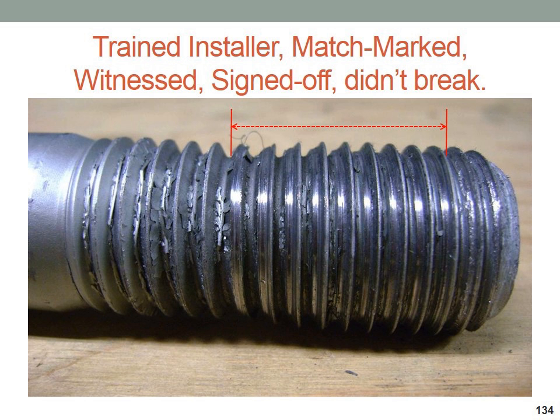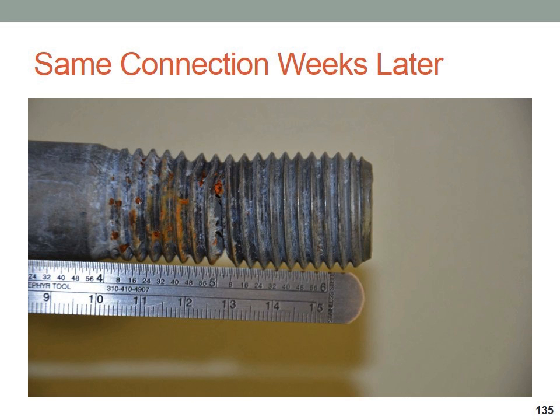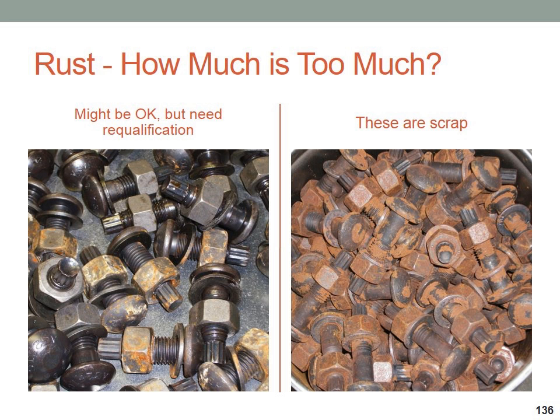And now that we're using coatings on A490, we've seen some very limited cases of stress corrosion cracking as a result of that high level of tension creating micro-fine stress cracks in the thread roots, which are then susceptible to sort of a delayed fracture or stress corrosion cracking. And that's one of the downsides that we're starting to see from some of the coated high-strength fasteners.